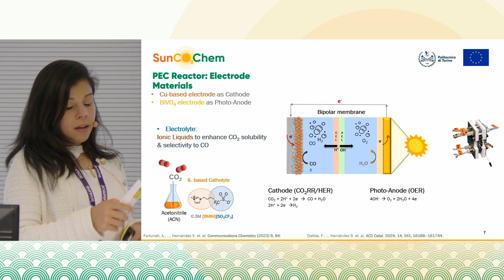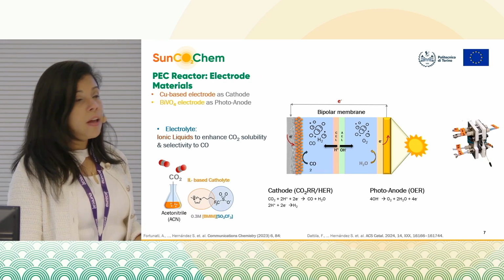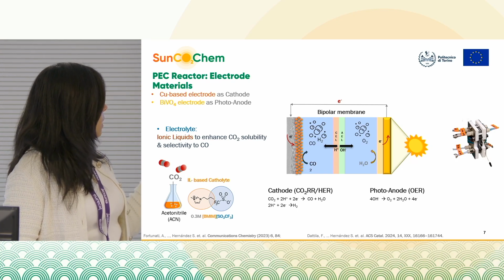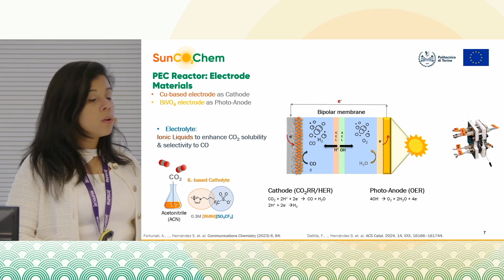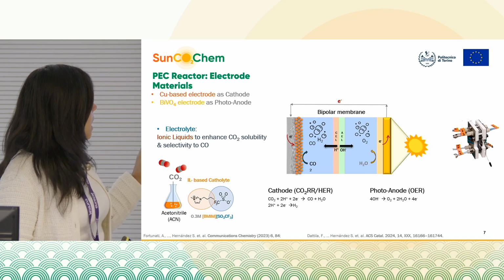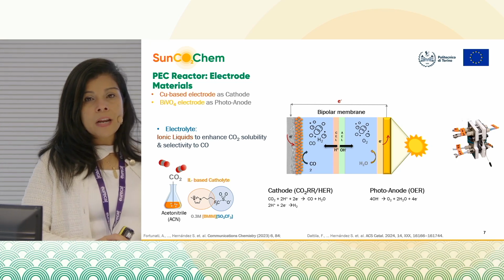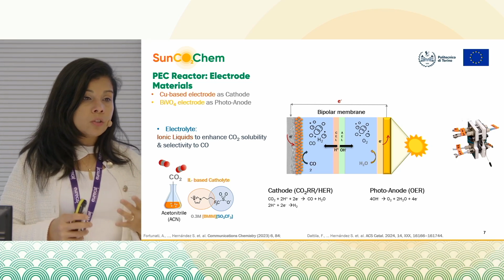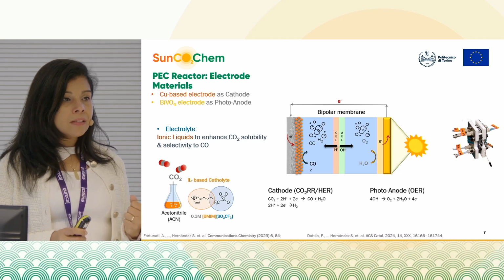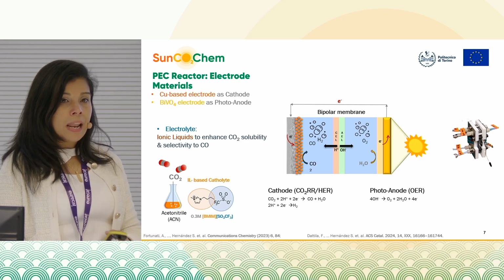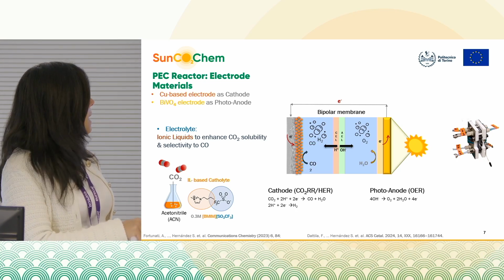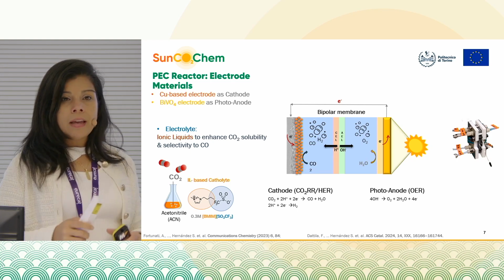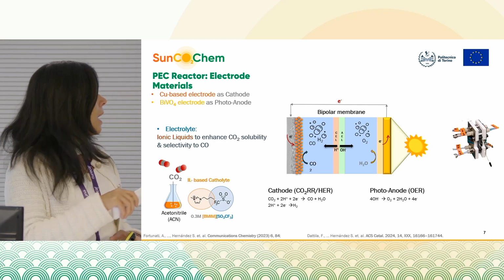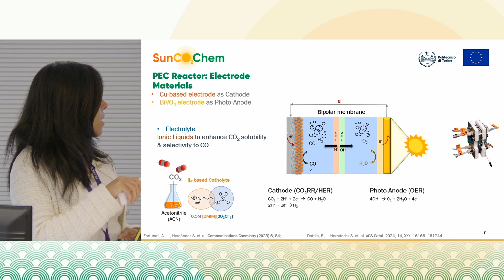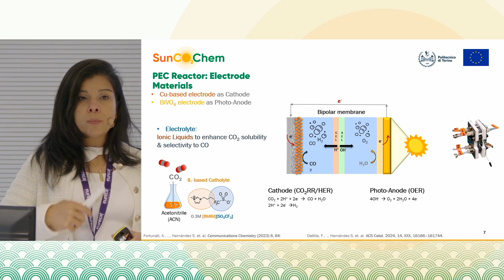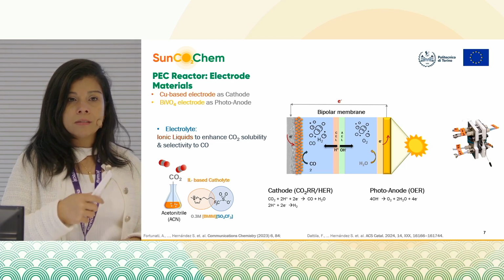So the materials that we developed were a copper-based electrode for the cathode and a bismuth-vanadate photoanode, and we started our research trying to explore the potentialities of ionic liquids for enhancing the solubility of the CO2 in the electrolyte, and in that way being able to concentrate the CO2 in the liquid media and have a higher availability of our reagent on the surface of the electrode to enhance the evolution of the CO, carbon monoxide.